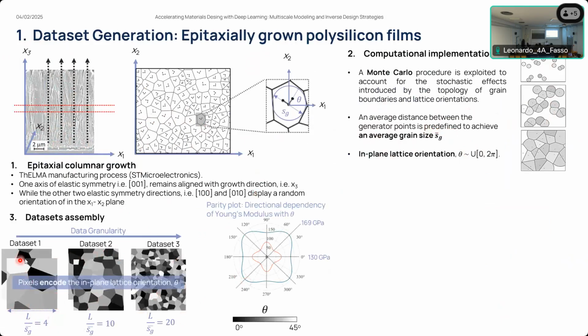Next, in the images, we can encode in the pixel values the in-plane lattice orientation, which is related to the directional dependency of the effective Young modulus. In particular, if we analyze the directional dependency of monocrystalline silicon, we will obtain this kind of trend, analyzing the parity plot. And we will exploit this symmetry in order to provide some additional experimental tests, which I will present later on in the result part.